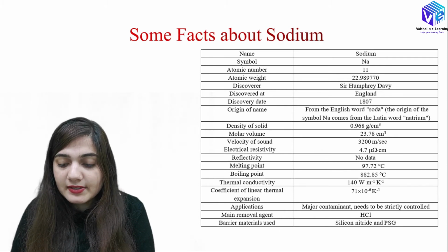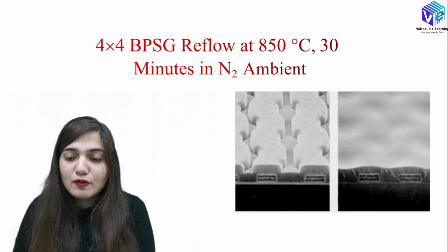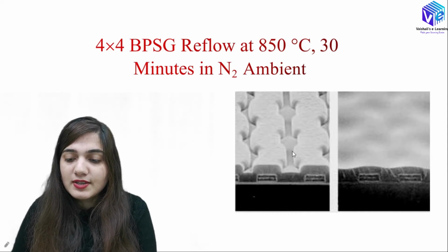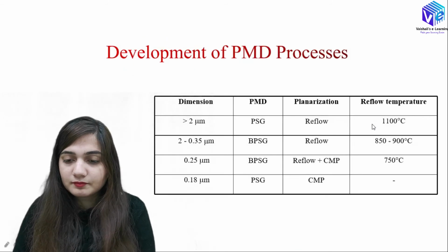Barrier materials used are silicon nitride and phosphosilicate glass. You can see the reflow process at 850 degrees Celsius for 30 minutes in a nitrogen ambient environment for the 4 by 4 borophosphosilicate glass. Here we have some non-uniformity, and when we give a higher temperature, it gives a uniform surface.